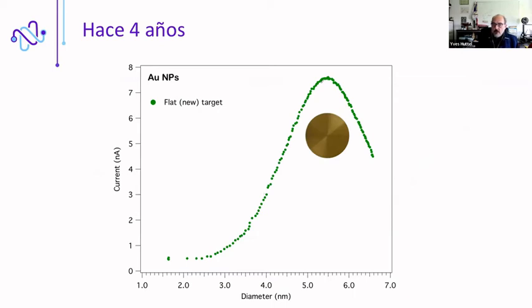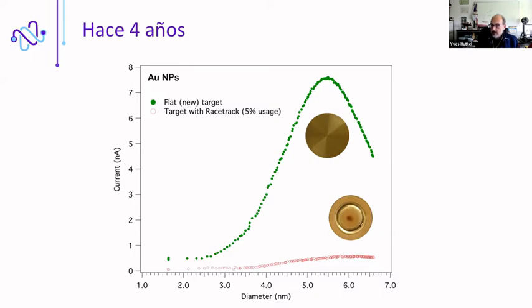Here I show you a curve where I have represented a current that is proportional to the number of nanoparticles we are fabricating. This curve was measured with a brand new gold target, flat surface. And we have compared the efficiency in forming nanoparticles with a used target, which has the racetrack I was talking about. As you can see, there's a huge reduction in the production of nanoparticles. This is a well-known problem in magnetrons.